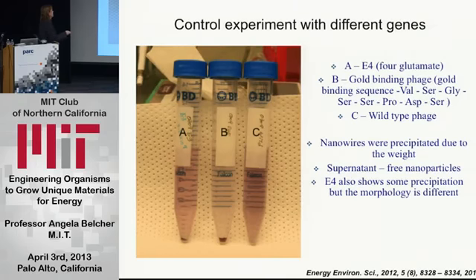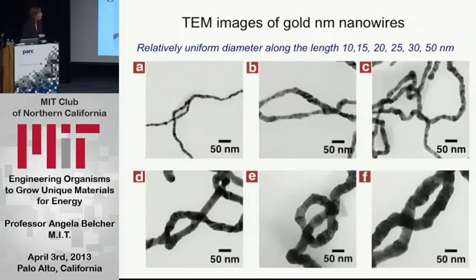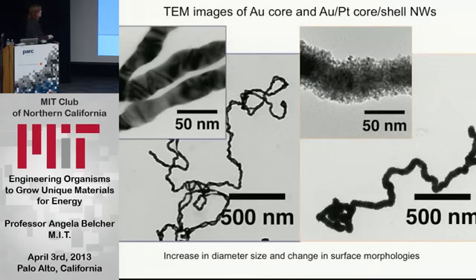And you have another clone that we use a lot for some of our battery work. And you get a little bit of precipitation, and then in a control you don't get any. Basically it becomes very specific for growing a particular kind of material. And this is some nanowires that we grew that are gold nanowires, and we could control the diameter of them. And then you can do other fun things with them, like start growing second materials on top of them.